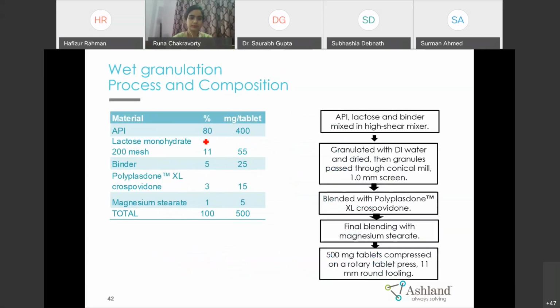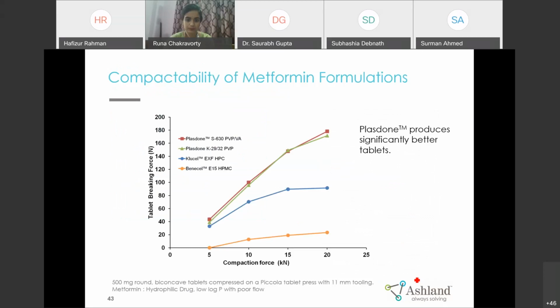We have taken batches where we used 80% API and 5% binder. How we manufactured these batches is, we blended API with diluent, which is lactose, and binder. Then we did granulation with water. After granulation, we milled the granules with a 1 mm screen to get uniform granules. Blended it extra-granularly with the disintegrant, lubricated with magnesium stearate, and compressed 500 mg tablets using an 11 mm round punch. We compressed tablets at different compression forces and checked the tablet hardness.